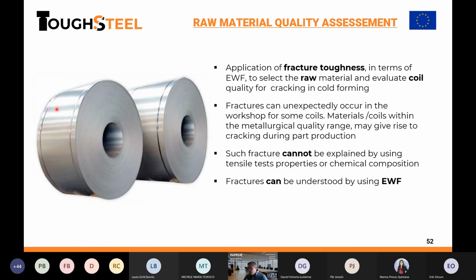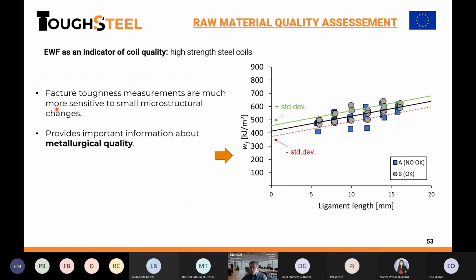We know that if you change the material supplier with the same steel grade, the same ductility, the same yield stress, sometimes the behavior is not so good. But this is not because of the ductility, and not because of the yield stress. It's because the toughness is different. And if we don't measure it, we don't know it. So let's see how it affects this. This is one example from a steelmaker in Europe that gave us specimens from different coils. Just by putting everything together, we detected a big scatter. This is not usual in fracture toughness measurements. The scatter is not that high.